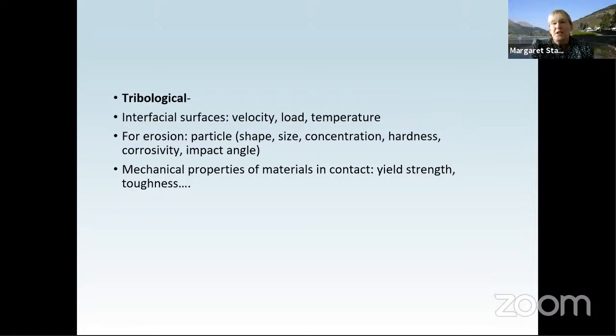For erosion, we have the various parameters associated with the particles. Say, for example, if it's a sand particle, the shape, the size, the concentration, and the hardness, and sometimes if the sand is covered by some sort of corrosion substance, for example if there are any pollutants in the water, such as sulfates, that can cause corrosion. We also have corrosion, with seawater affecting the erosion on the surface and interacting, and there's a whole science of erosion-corrosion, or at least mechanistic interactions, and the impact angle that the surface presents to the particle. And obviously there are things like the mechanical properties such as the yield strength and the toughness.